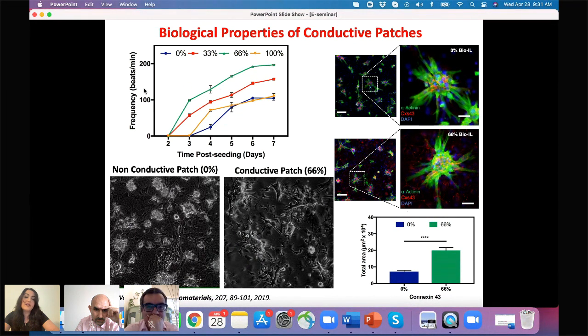We culture the cells on all these substrates, and here I put a video from the non-conductive patch. This is the blue line. We had some beating, but the cells were not beating synchronously. However, when we cultured the cells on the conductive patch with 66% bio-IL, we had higher beating frequency and more synchronized beating of these cells cultured on the substrate. So the cells respond to the level of conductivity in the substrate.